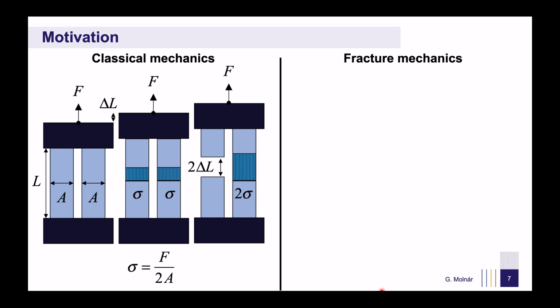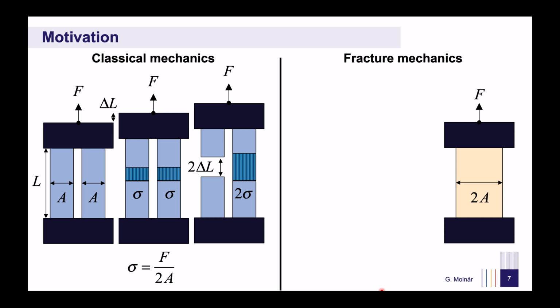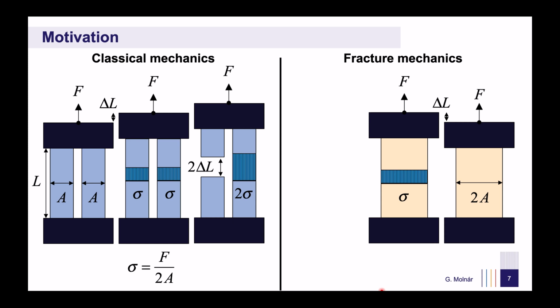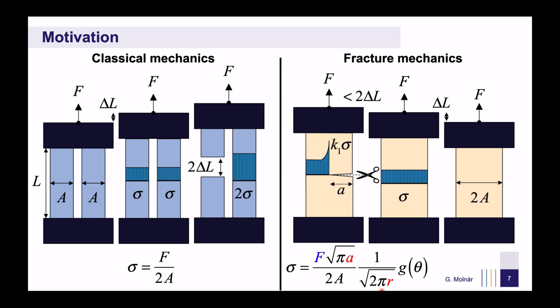increase in stress. Now suppose we glue the 2 columns together with an extremely strong adhesive. If we apply the same load, the stress remains identical to the original intact case. However, if we cut the sample at the center, we create an infinite stress peak. As a result, traditional mechanics cannot predict when the structure will fail using a simple stress-based strength criterion.